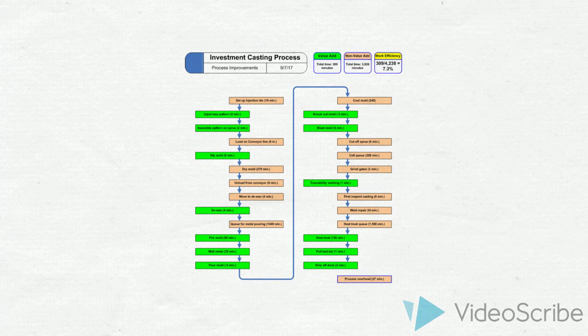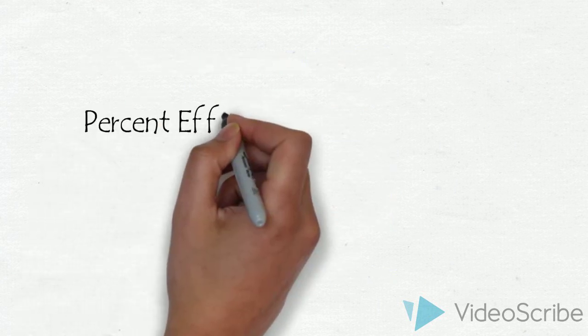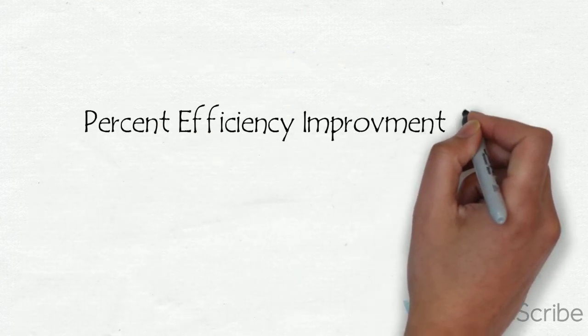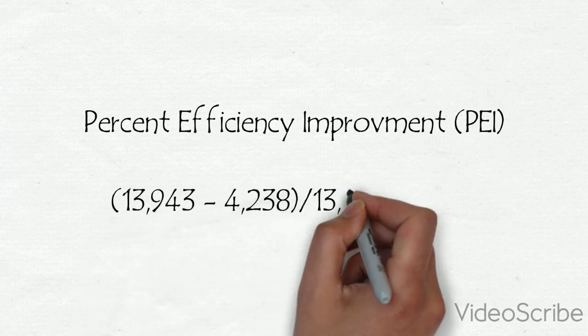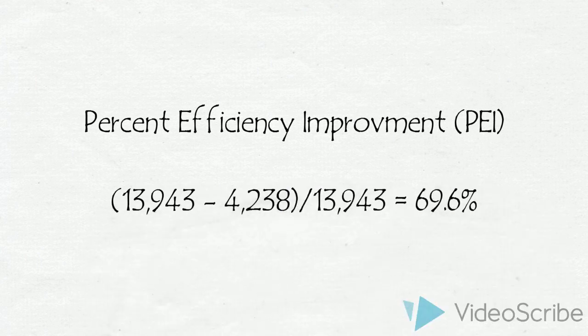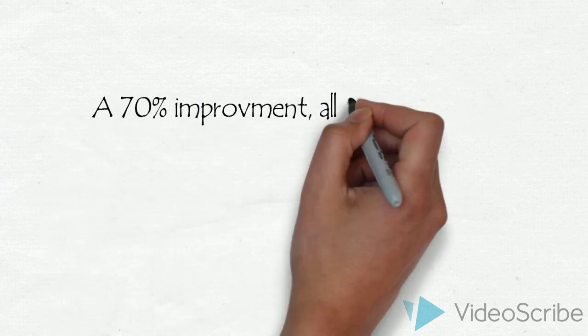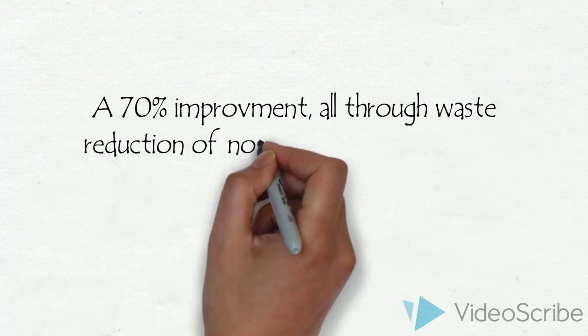To wrap it up, I calculated the process improvement efficiency using the total process times from both the current and optimized states. The PEI landed at 69.6%. So basically, a 70% improvement by focusing only on waste reduction within the current process.